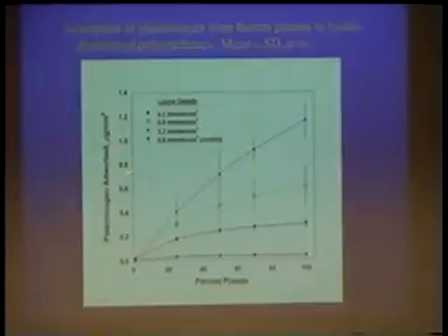So it's adsorption of plasminogen this time, and percent plasma on the x-axis. These are the four surfaces. This is the control, which has lysine on it, but in which the alpha amine group is free, but not the epsilon. The epsilon is tied up. And there are three surfaces with lysine on them, where the epsilon amino group is free, but at different densities. It's interesting to compare this curve, the black one, with the green one.